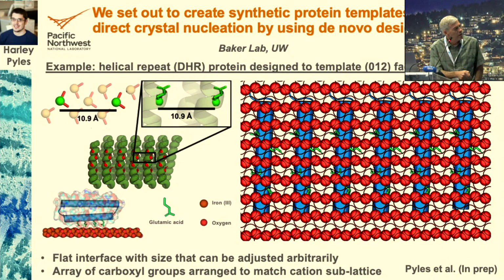Now, along the alpha helix, you can put in different amino acids. We're using glutamates, which present carboxyl groups. And we can arrange the carboxyl groups to match any array of cations. So the idea is to match the array of carboxyls to, say, the cation sites on a mineral surface. In this case, this is one that Fatima designed to bind to the (012) face of iron oxide in the form of hematite. And when you put it down and look at it with AFM, they're all aligned on the (012) face in a certain orientation.